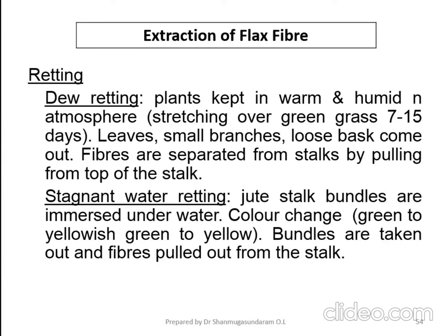Okay, stretching over green grass for about 7 to 15 days. So while keeping the plants in this situation, what will happen? The leaves, the small branches, and loose bark comes off the plants. The fibers are separated from the stalks by pulling from the top of the stalk. So this is one type of retting process. You can extract the fiber from the plant.